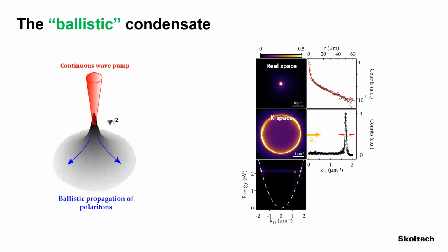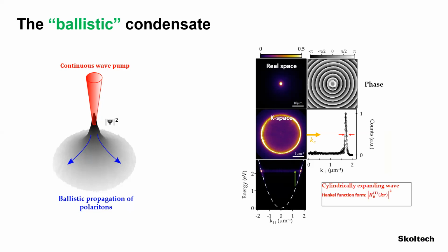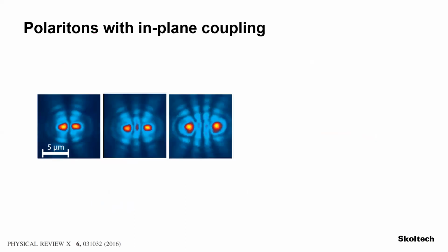So imagine now that this condensate expands in the plane, and I will go and actually measure the phase of one condensate. These are experimental measurements. You can see that the phase is a cartwheeling phase, yes? So as they propagate in the plane, the phase cartwheels between 0 and 2 pi. And now what will happen if I put two of these condensates? So this is a real space photoluminescence image. One condensate, another condensate. If I increase the separation distance, I see fringes forming in between.